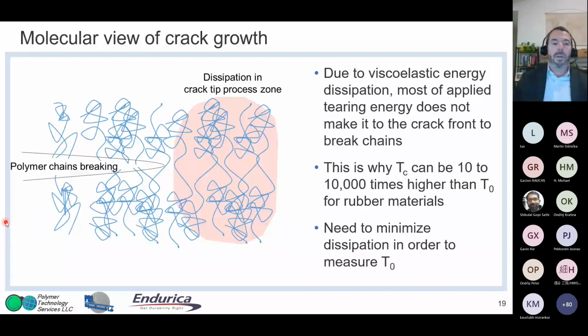Why is that so difficult to measure, the breaking of polymer chains? Well, when you load up the rubber from the far field, not all that energy actually makes it to the crack tip. A lot of that energy gets dissipated in front of the crack and never makes it to breaking the polymer chains. And so that's why the tear strength of rubber can be 10 to 10,000 times higher than this fatigue threshold for breaking all the polymer chains. The tear strength in magnitude is 10 to 10,000 times bigger than the amount of energy it takes to break the polymer chains. And that's because of dissipation. Some people view hysteresis and energy dissipation as something negative in rubber compounds because of heat buildup and because of tire rolling resistance, for example. But if it wasn't for viscoelastic energy dissipation, rubber would be a very weak material. So hysteresis is our friend when it comes to resisting damage development inside rubber.